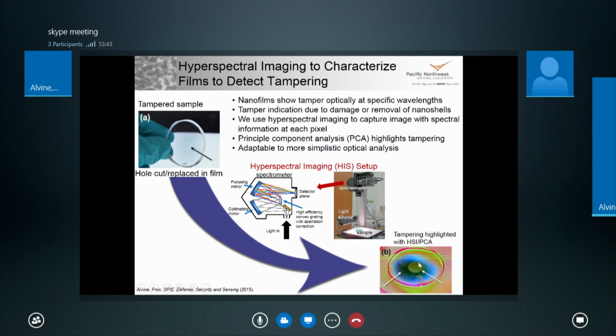But then when you look at multispectral analysis or hyperspectral analysis, you can see that that center structure was definitely tampered with, and also there's a sort of damage region around it. And so it's designed to not show up in the visible, but to show up in the infrared, and that makes it a lot more difficult for someone who's tampering to be able to correct for what they've done. So it's essentially an added security feature.